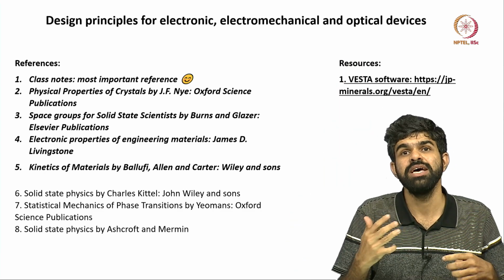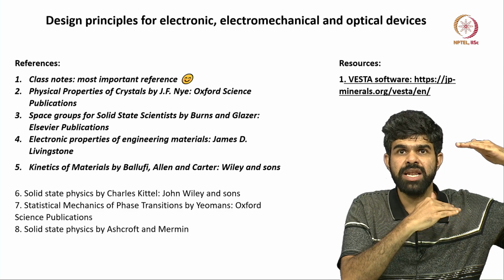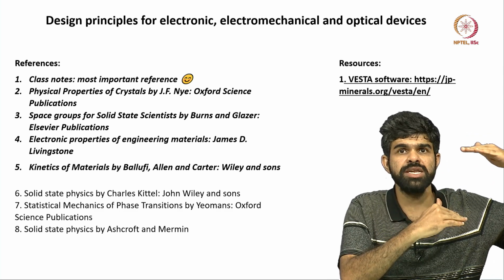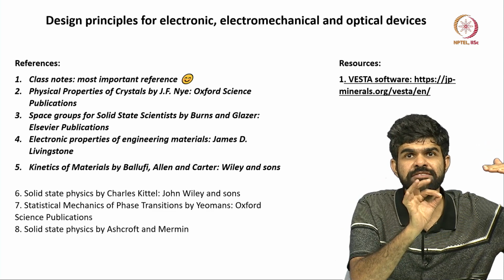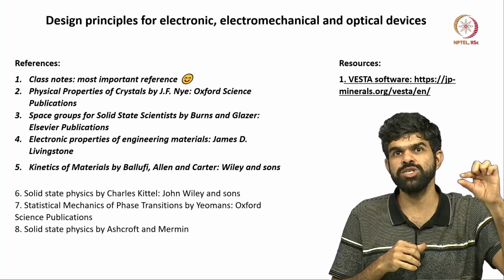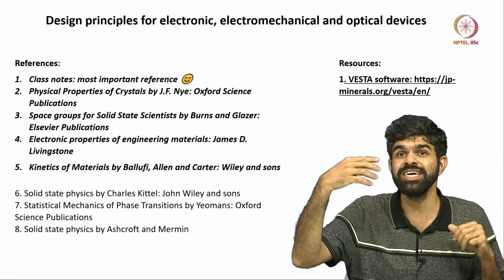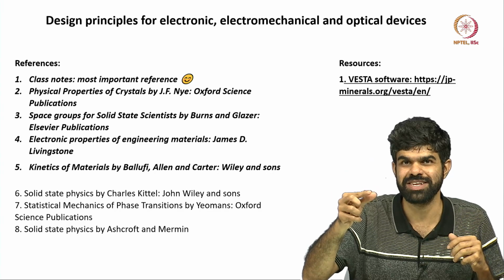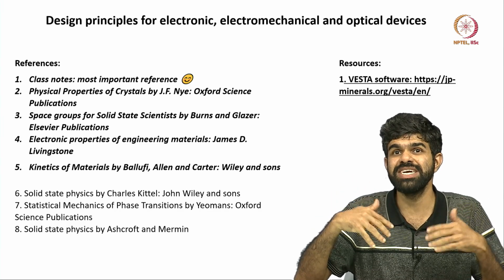Something like that. Or in NV centers, right. A diamond, for example, has an electron transition only at 6 electron volts, right. So, interband transitions at 6 electron volts. But if I put in a defect, I engineer the diamond, I put an NV center in diamond, then I am creating these 2 states, those are qubits, right. So, I have engineered a qubit in diamond by putting in defects, okay. That is the engineering part, right. That is how I design my materials.